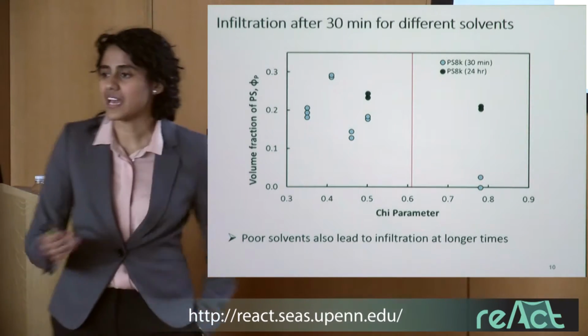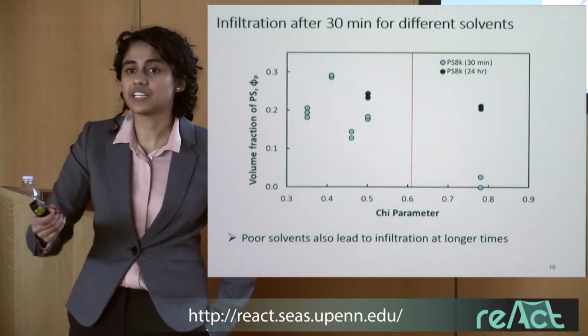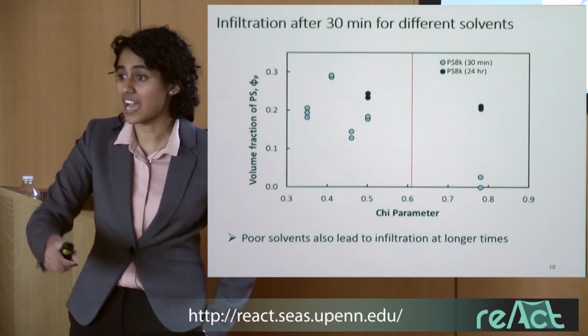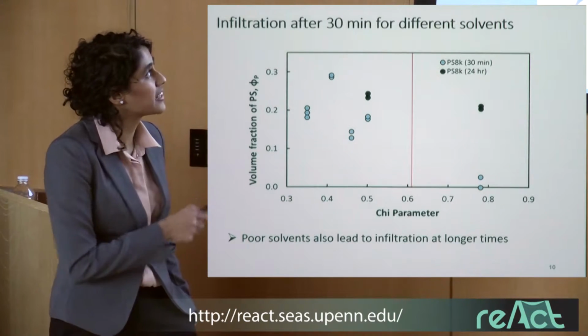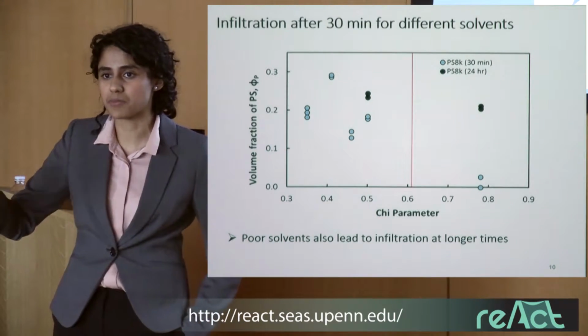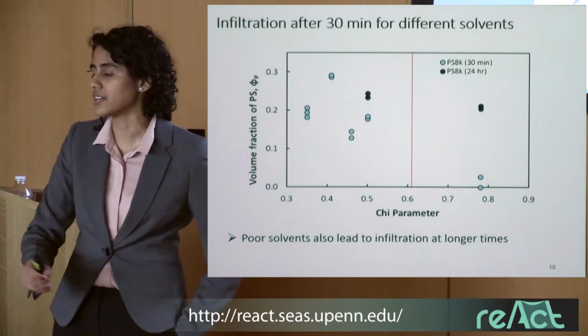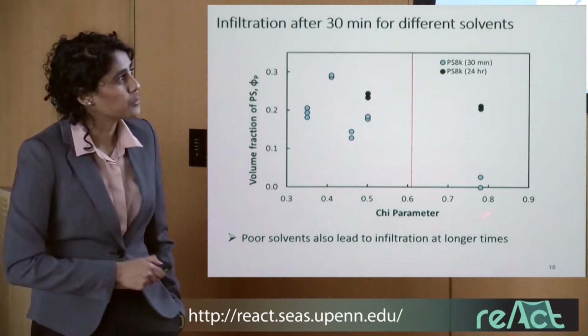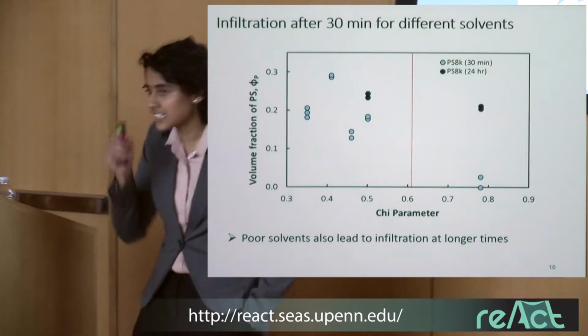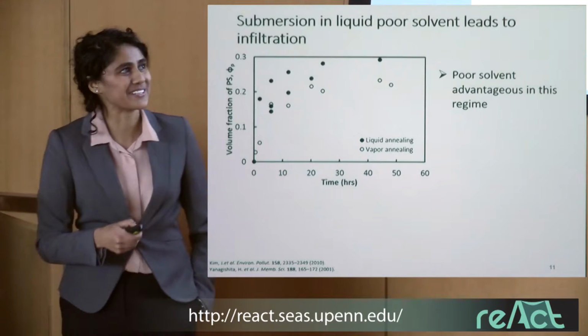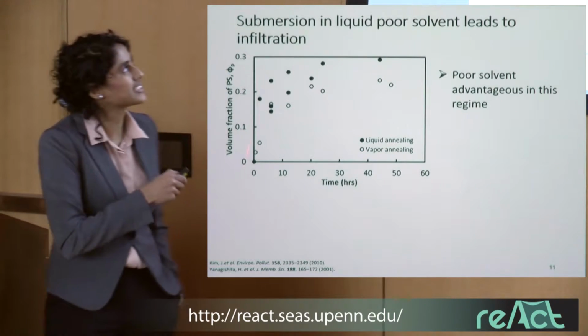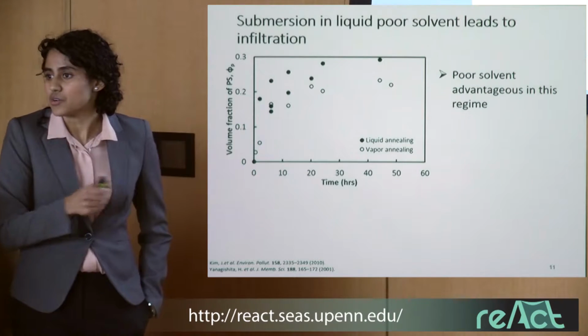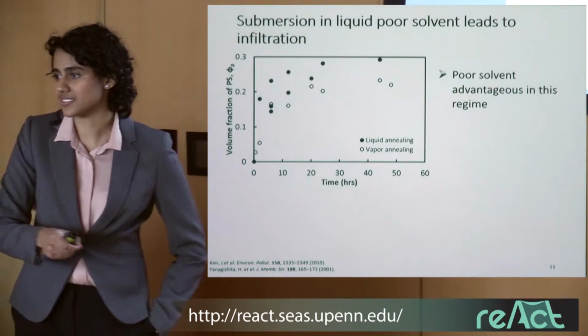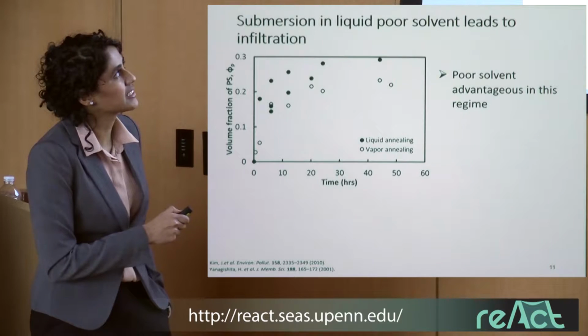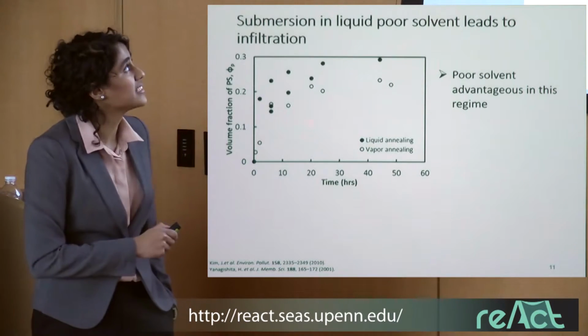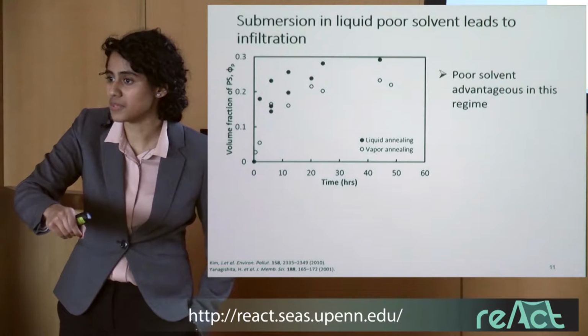So basically, if you can imagine, rather than solvent annealing, it would be great if we could just directly dunk these films and have them infiltrate. And the problem with this area over here is that it completely de-wets. My polymer completely leaves my substrate if I dunk them directly into liquid solvent. However, with a poor enough solvent, I can actually directly dunk it, for lack of a better term. And what I see is that infiltration occurs, given enough time, with direct liquid annealing of these systems. And this is compared to the vapor annealing. The open circles are vapor annealing, and then the closed ones are just direct dunking of my films, my bilayers, into my liquid solvent.